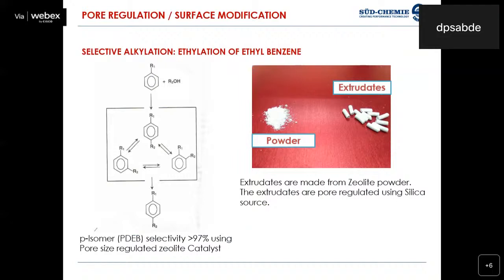So if you look at the application like the ethylation of ethyl benzene, basically using an ethyl alcohol, there are three different products which are expected. Basically, one is the ortho isomer, the other is the meta isomer, and the third is the para isomer. But normally, it is possible to change the selectivity to the para isomer, which is commercially more important, by doing some surface modifications of the catalyst.